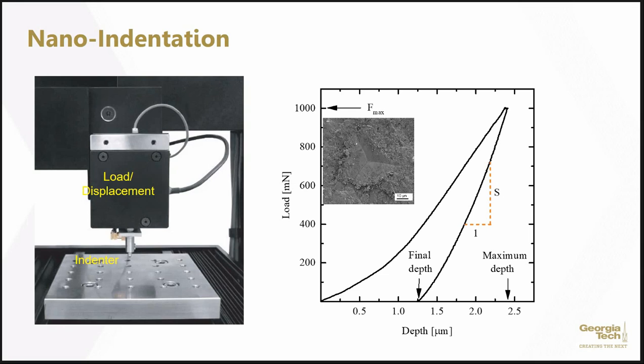Now, this is a very small scale, right? So the scale bar probably is not clear. The scale bar here is only 10 microns. You can see that we apply only 1,000 millinewtons. That's 1 Newton of force, and that will penetrate into the specimen to 2 microns, 2.5 microns, right? 1 Newton of force is very small. It's like the weight of an apple. So that's a tiny force we apply. Since most of the stress is concentrated in a small area, you are still able to deform the specimen surface and get the material properties measured.